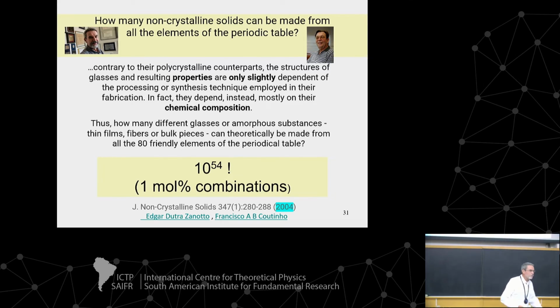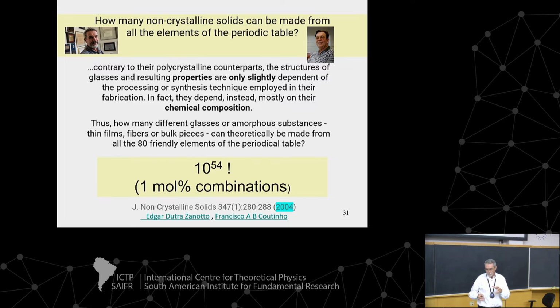That's a very good one. Amorphous materials do not show a glass transition. You can pick a crystalline material and hammer it, breaking the long range order, and you form an amorphous material. Or you can evaporate a material onto a thin film, onto a cold substrate, and you can form an amorphous material.